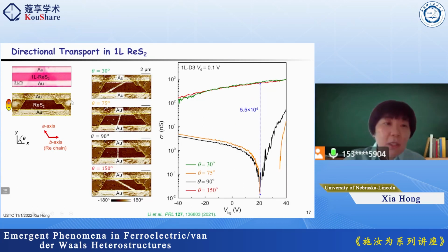So now we have this improved field effect. We're going to define the entire channel into the insulating state and write domain nanowires in different directions, and measure the resulting conduction. So you can see that we work with exactly the same channel, and by simply varying the nanowire direction, the transfer curve changes drastically.